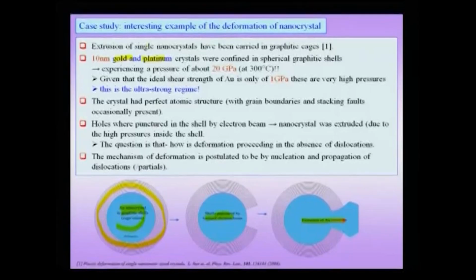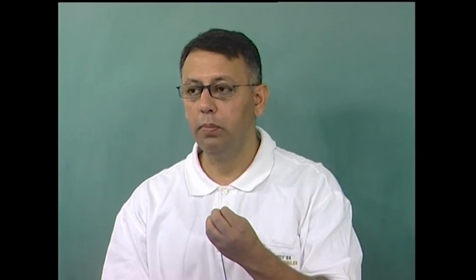So, this is a later version of this experiment, wherein this high pressure has been used for the extrusion of gold. So, in this experiment what they do is that they take a carbon onion and then using these graphitic cages they extrude gold or platinum. The size of this nanocrystal is about 10 nanometer, which is present inside this, the blue color thing is about 10 nanometer, and this is a confined kind of a nanocrystal. The pressure experienced at about 300 degrees Celsius is of the order of 20 GPa.